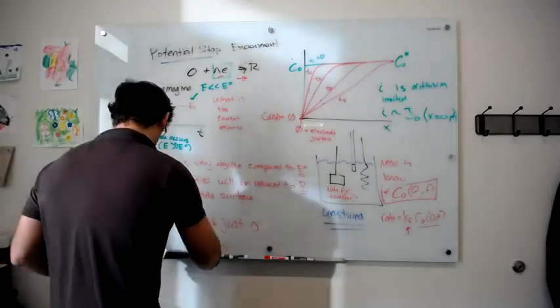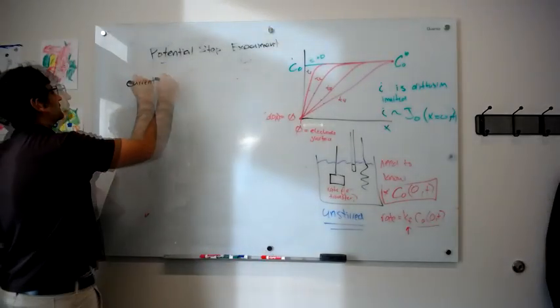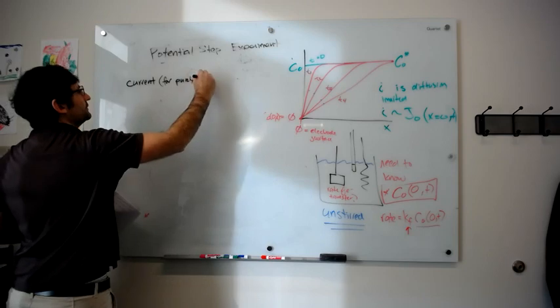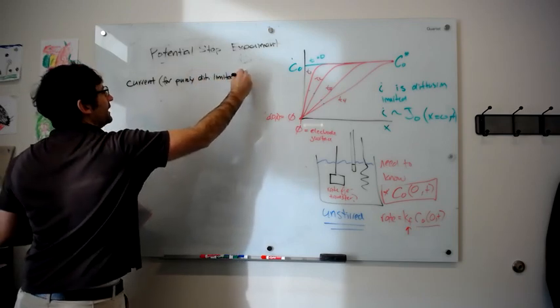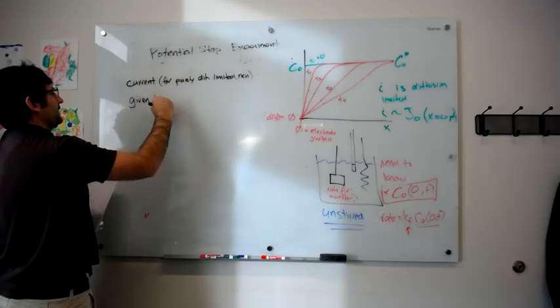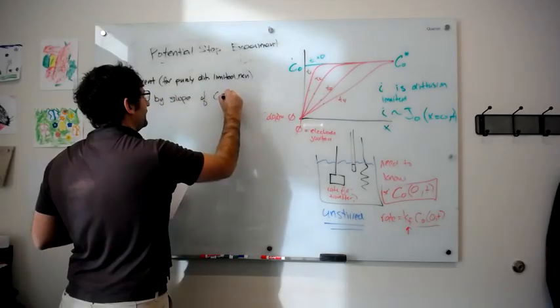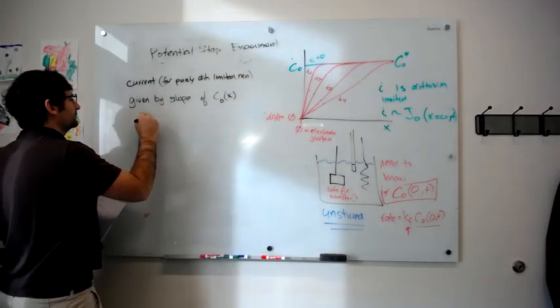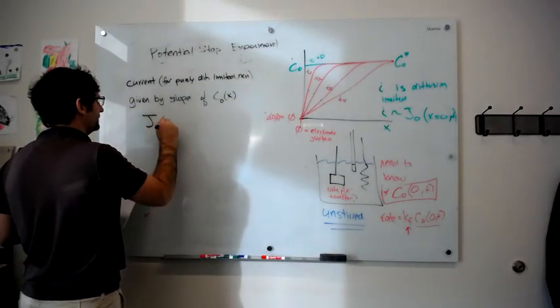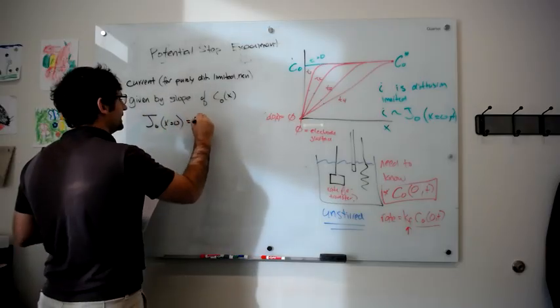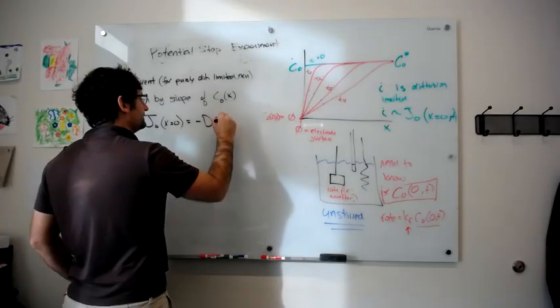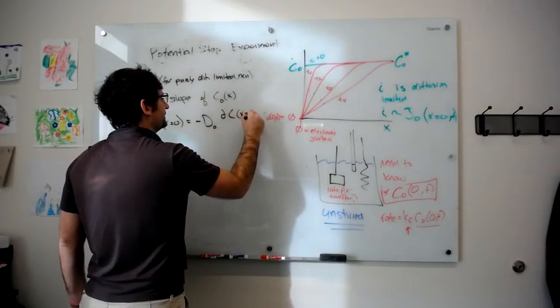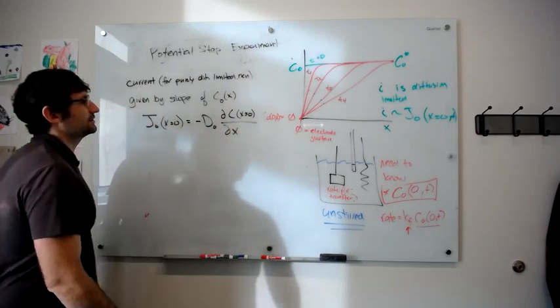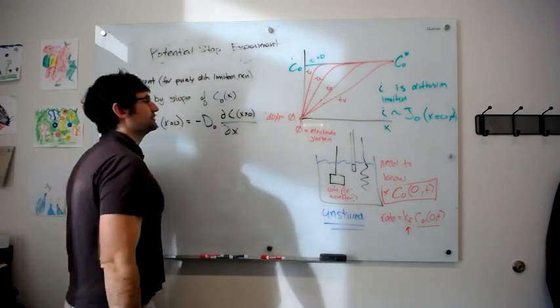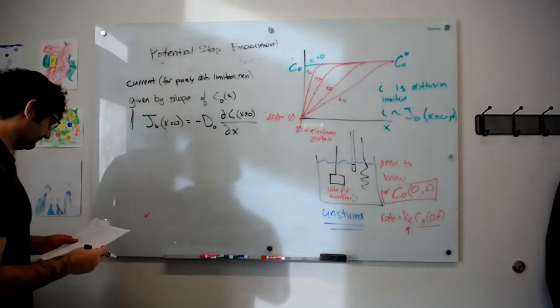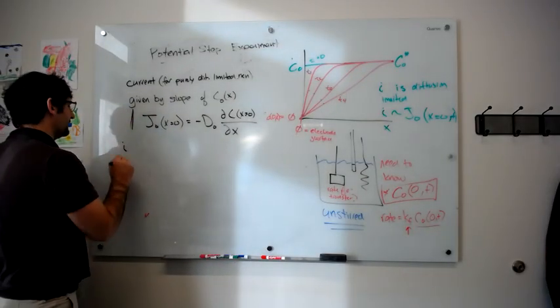Okay, so let's go through that now in a little more detail. So, current for a purely diffusion limited reaction is given by the slope of C of x, in this case C_O of x, which is equal to J_O at x equals 0, equals negative diffusion coefficient of O times dC_O at x equals 0 over dx. So it's the slope right here at the electrode surface. Okay, and that's going to tell us the flux of O. So what's going to happen as a function of time?